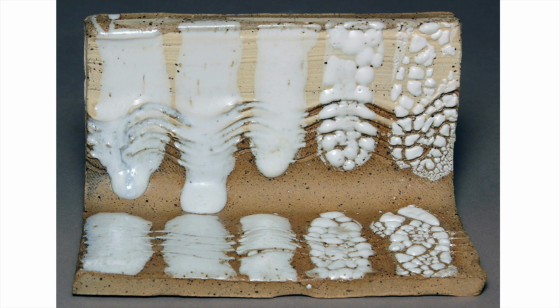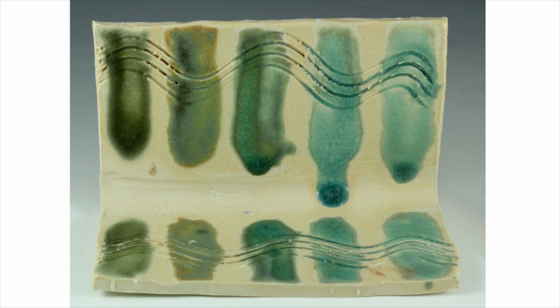As in this example, where magnesium carbonate - this test shows the influence of magnesium carbonate when added in increasing amounts to a simple base glaze. I can then choose which stripe produces that particular quality that I like with the correlating amount of the influence ingredient, which is written on the back of the test tile, and then make up that glaze.